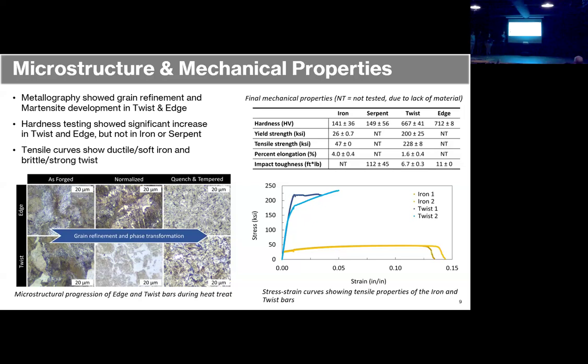And if we look at impact toughness, that's actually where we just take a bar of the material and we swing a big hammer at it basically. And we measure how much energy is taken out of that swing from the material. So you can see that the serpent, it was 112 foot-pounds, and compared that to the twist and edge, which are about 10. So it's an order of magnitude higher toughness for our serpent samples.